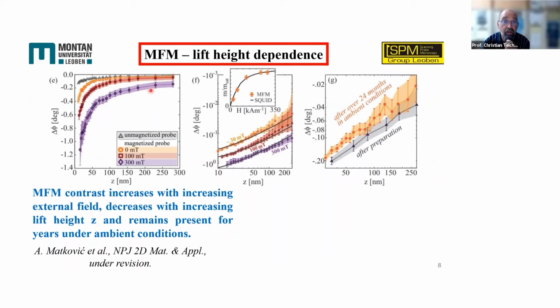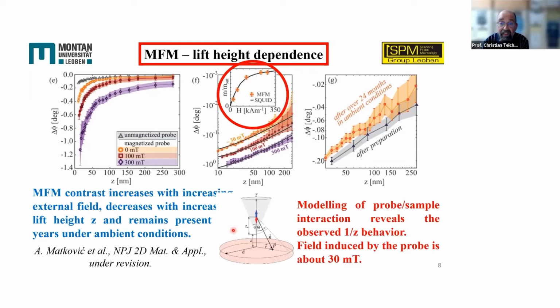And we measured the magnetic response in the 2-pass technique as a function of the lift height. And you can clearly see that with increasing lift height, we have a decrease of the response. Here the black curve is the unmagnetized probe with more or less no response. And here we see that we can match the MFM signal with the SQUID signal. So we have a 1/z dependence of the magnetic signal by assuming that we have a disc-like magnetic sample and a conical probe. Then we really find this 1/z behavior, and by simple calculation we can estimate that the AFM probes that we use are inducing about 30 millitesla.